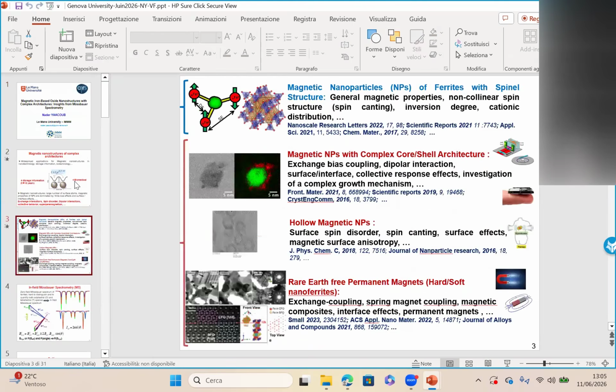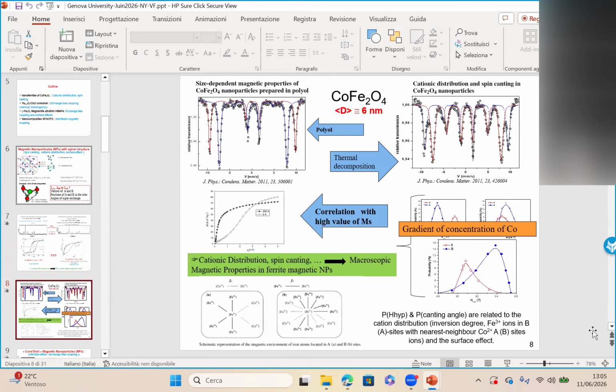About this one, it was the first collaboration with Davide, from, I don't know, now 15, 16, 17, 20 years. So this is the spectrum mentioned by Jean-Marc. It needed 1 year to arrive at this fitting. The fitting presented here, we can easily see we have some correlation. But the problem is we have some overlapping. So we normally need another technique, using the inversion degree obtained from neutron diffraction and the mean magnetic moment directly obtained by neutron diffraction, used here on the distribution in order to obtain the magnetization at saturation at low temperature. So it was like a ping pong during 1 year between the different techniques to arrive at this conclusion.